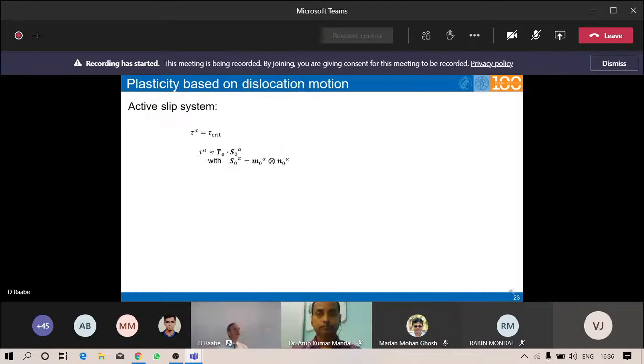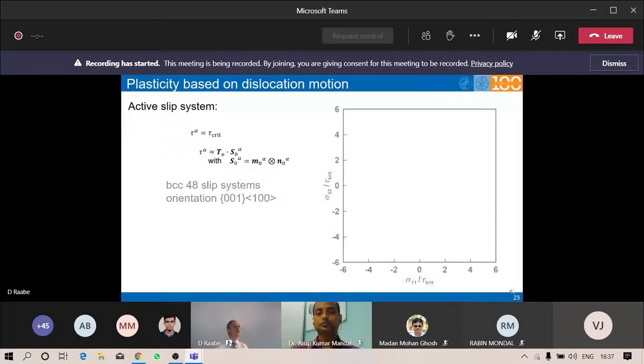Now a bit of the kinematics, because I told you all of this has to be written in dyadic form, in tensorial form, and not in scalar form. And here you see again a very simple textbook equation from my classes on micromechanics when we pick a body-centered cubic crystal structure and assume that you have 48 slip systems. You can, for each of those, calculate what you know typically as a Schmid factor, which is, of course, again a Schmid matrix or Schmid tensor.